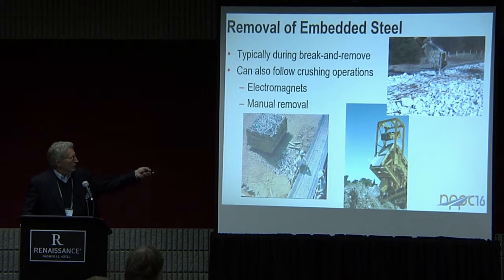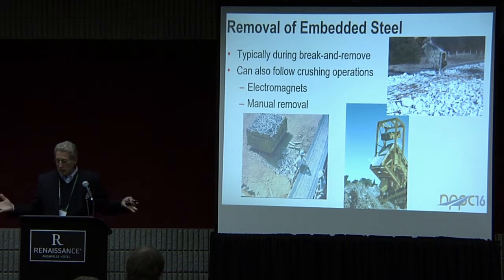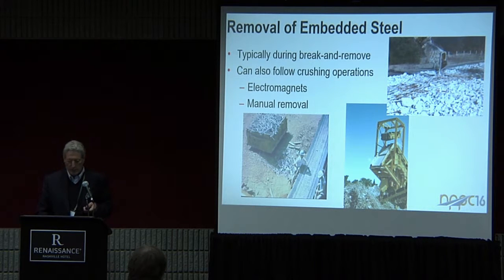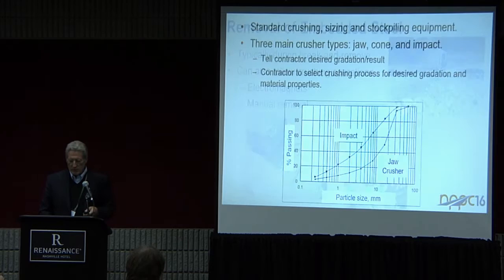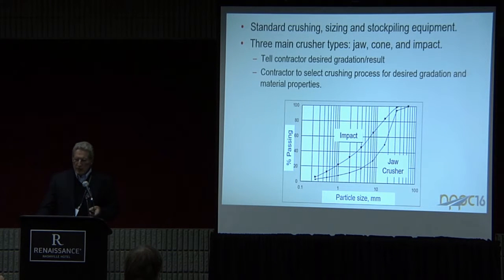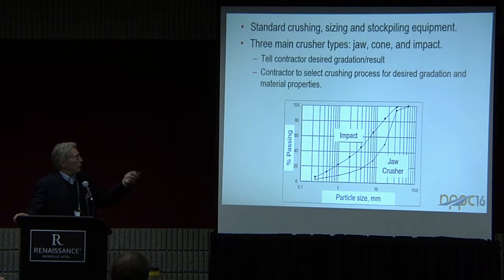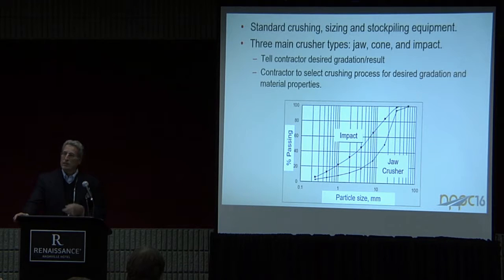So removal by hand, you can see them pulling the stuff off, or with an electromagnet, as you can see here, and depositing it down on the side. And that again is another recyclable material. Usually we find that the cost of recycling that steel pays for the cost of doing the removal, and maybe a little bit more. You can use standard crushing and sizing equipment. Mainly we got jaw crushers, cone crushers, impact crushers, typically a two-stage process, a primary crusher and a secondary crusher. What you really want to do is specify what you want that gradation to look like and let the contractor figure out how to crush it, because there are different gradations of materials going to be produced with different crushing processes, and even with different aggregates and different mix designs.